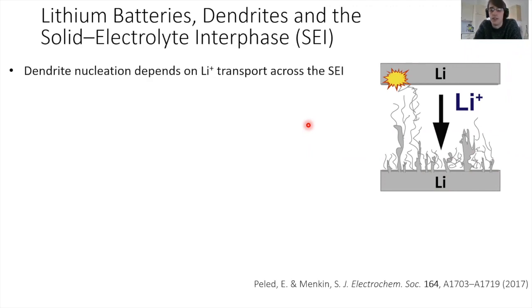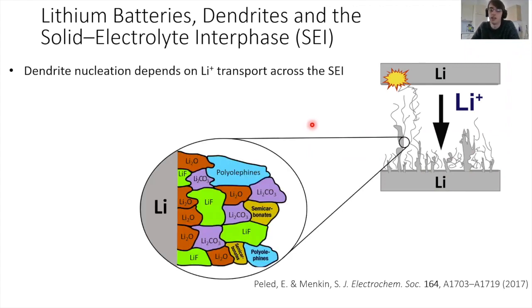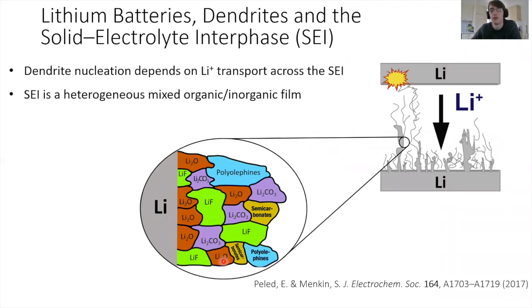It turns out that the nucleation of these dendrites depends on lithium transport across the solid electrolyte interface. This thing here. This is a mixed inorganic, organic, heterogeneous film that passivates the surface of any exposed lithium metal, so including on the dendrites. In general, this is quite a challenging species to study because it's heterogeneous, it's nanoscale, and ideally you want to form it in situ. In particular, we want to study this interface here because that's where the nucleation happens, right at the interface between the metal and the SEI.